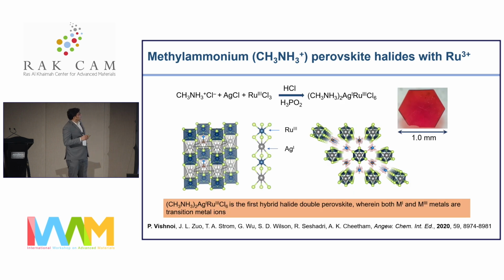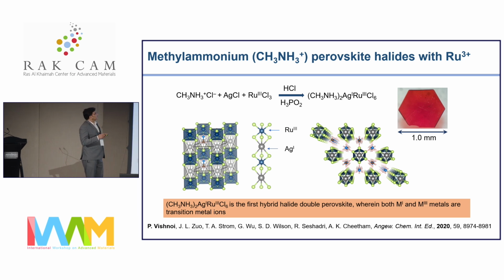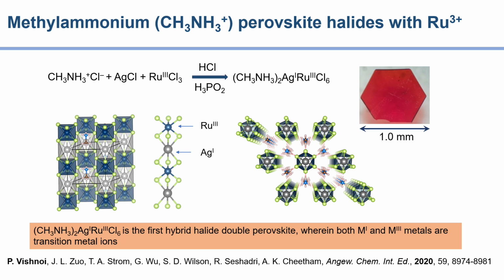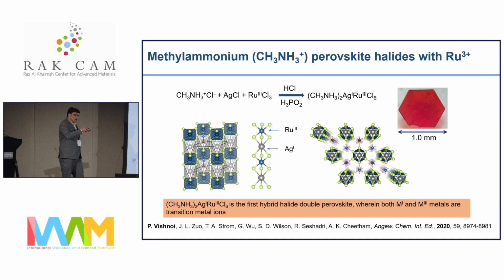We started to work on a hybrid system, choosing methylammonium as the cation to go in the cavity. We carried out this reaction, and we found this composition by elemental characterization, and a beautiful hexagonal crystal, of course. But the structure of that crystal suggested it's not a 3D perovskite. It's rather a 1D chain, formed because of face sharing of the octahedra, where the opposite faces of each of these octahedra face share in one dimension, typically the C axis. In this compound, silver and ruthenium order alternatingly in the chain, and the 1+ methylammonium cation sits in the interchain gap and forms strong hydrogen bonds with the chain to make the lattice stable.